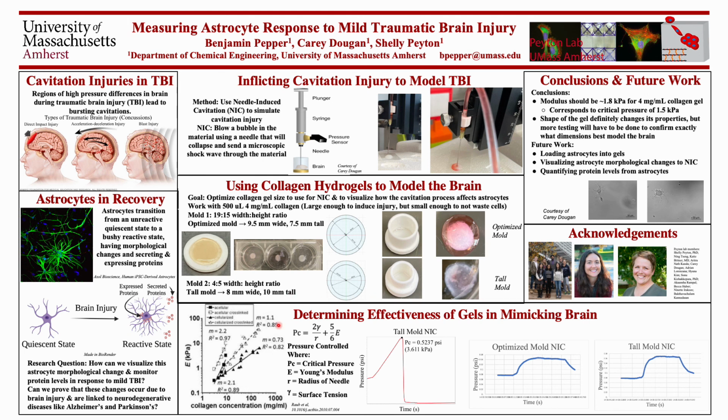From literature, we know that the Young's elastic modulus of the brain is 1 kPa. For gels, it will be slightly different since it doesn't have all the various cells and the products from all the cellular processes being produced in it that the brain does. However, in a paper by Raub et al., it can be seen that gels follow a general trend. In the graph of this trend that you can see here, for acellular cross-linked 4 milligram per milliliter collagen gel, we are looking at an elastic modulus of about 1.8 kPa.